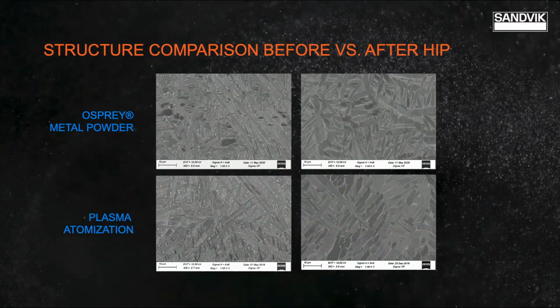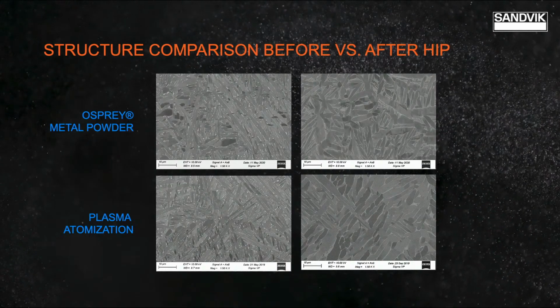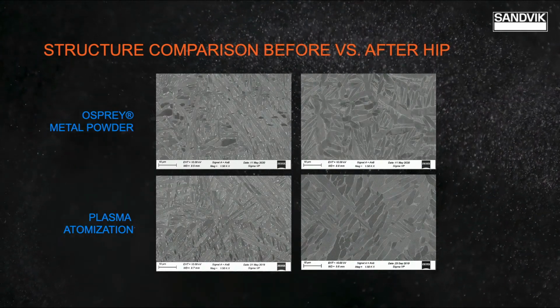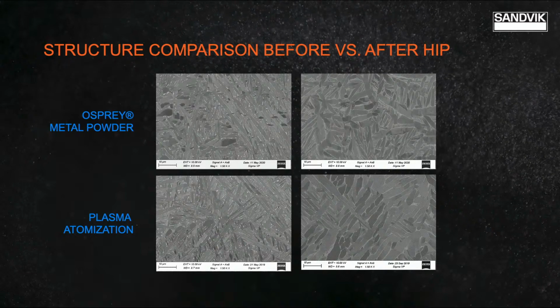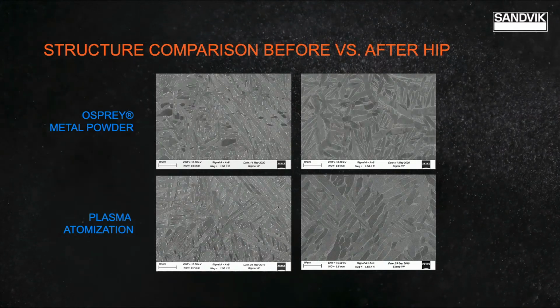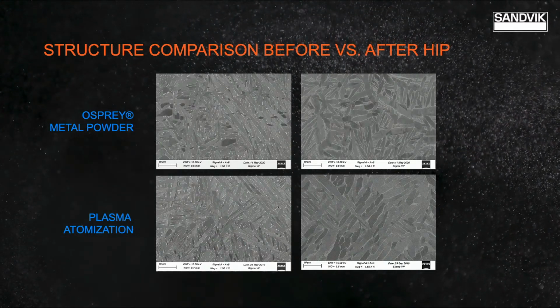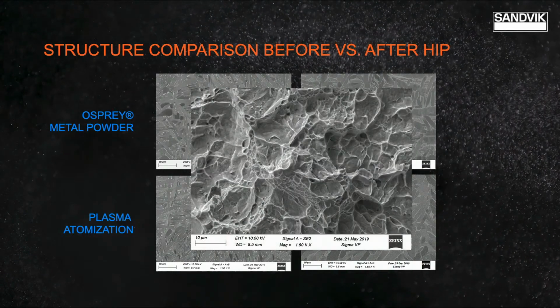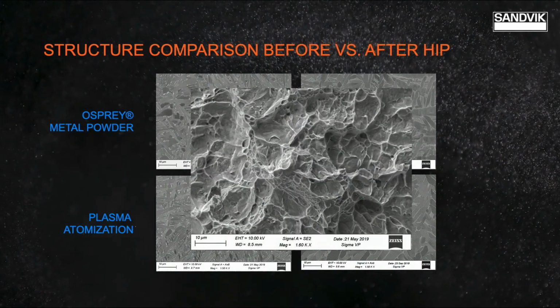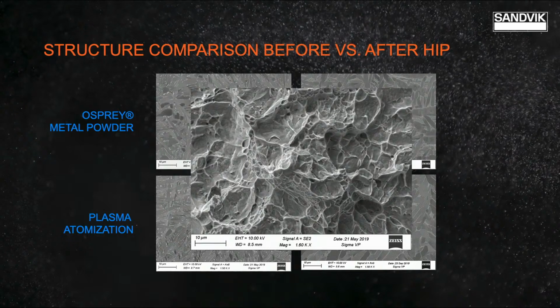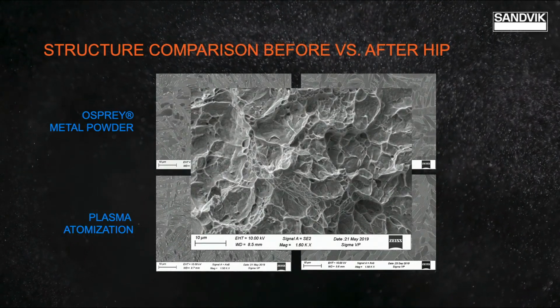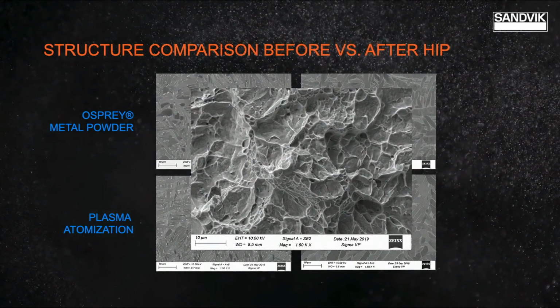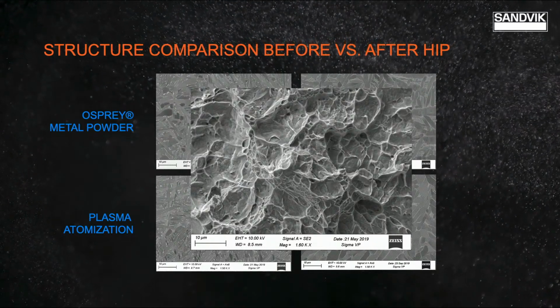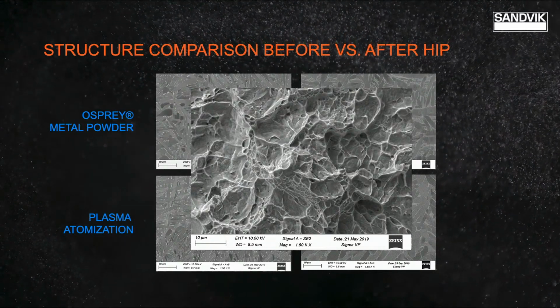And when we consider even other methods like the plasma atomization, we can see that there's very small difference between them. The next image also shows us a fracture surface for an impact toughness test that we did. And we can see overall that we have a very ductile surface that indicates a very good plasticity of our material. So it appears, after all, that the Osprey titanium powder shows very good characteristics.